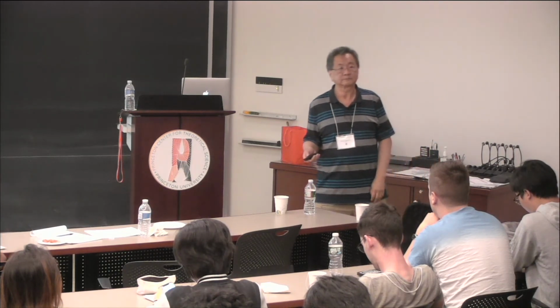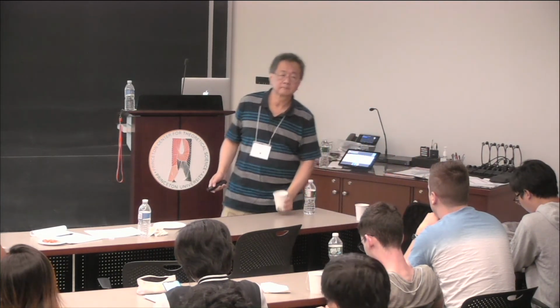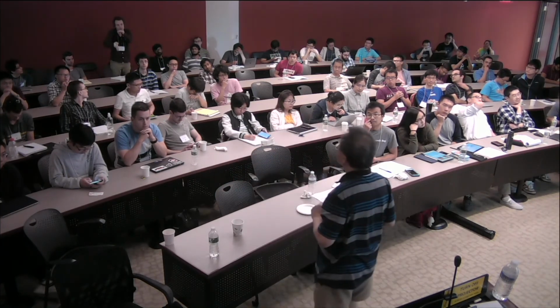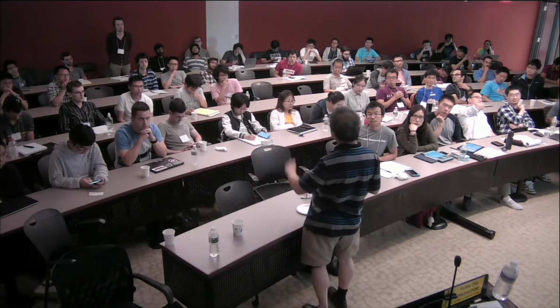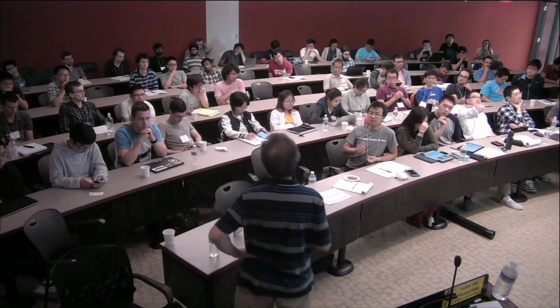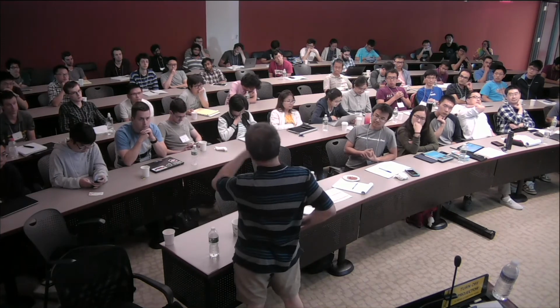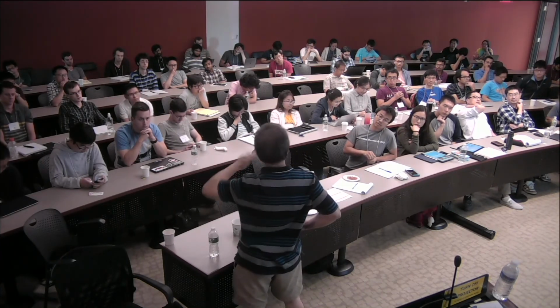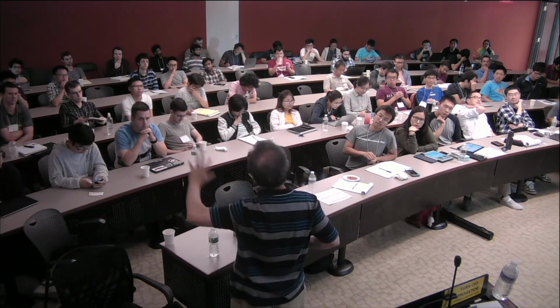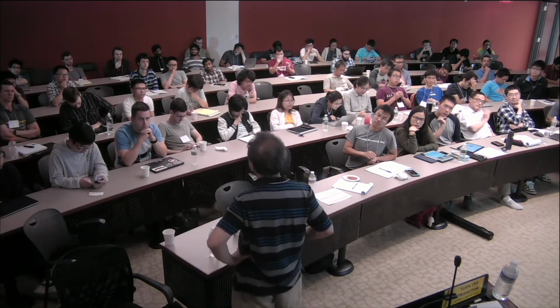When you discuss the edge currents, this somehow suggests a two-dimensional picture with a one-dimensional edge. How would you think about a finite thickness? Good question. We think that there are 100 layers, so the edge current is actually on the side wall. So there is some dispersion also in the z direction. Perhaps, but there are only 100 layers. Yeah, probably, so there are 100 modes. It cannot be two-dimensional because, as I stressed, a single monolayer will not have any screening at all. And you won't see chirping, you won't see the flux penetration phenomena. It's got to be finite thickness.